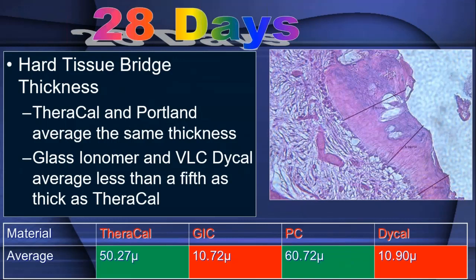And we measured the hard tissue bridge formation at three different places, at three different sections at 28 days, which is what the FDA guidelines called for. We found that the Portland cement, the MTA, was better, but statistically the same as the Theracal, and the glass ionomer and the Dycal were almost exactly the same in their hard tissue bridge formation.